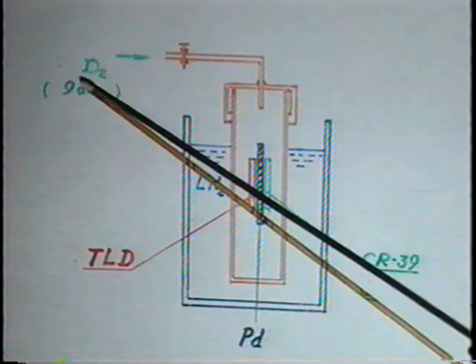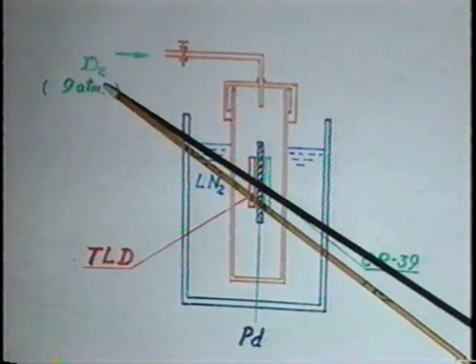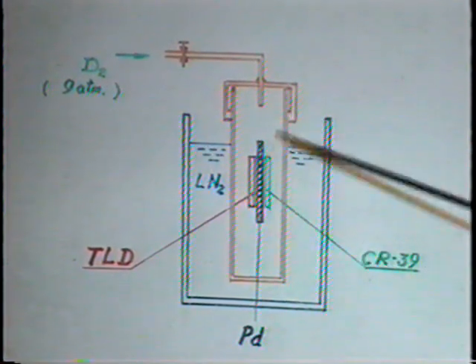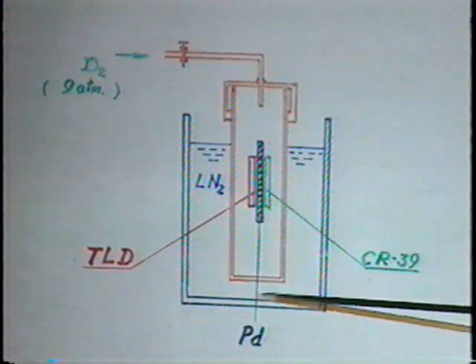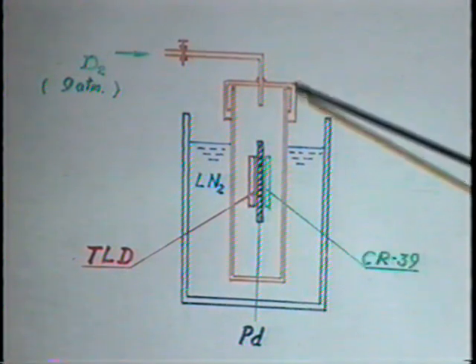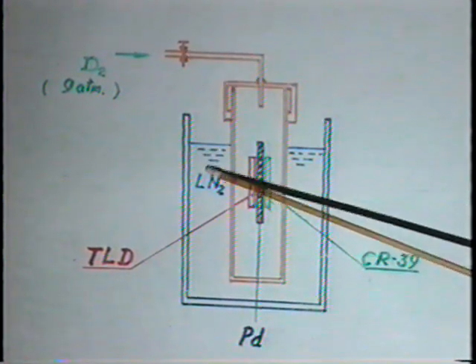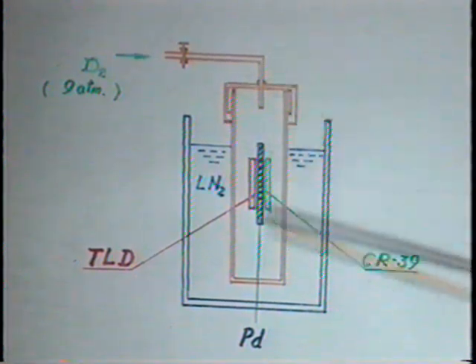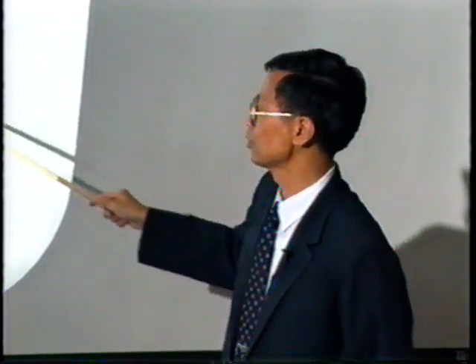Usually we put in deuterium gas at about 9 atmospheres and cool it down with liquid nitrogen in a dewar. Then we seal it. When the liquid nitrogen evaporates, the temperature goes up. Then we just do this cycle, high temperature, low temperature cycle. After this, we take them out and watch the image on the CR39.